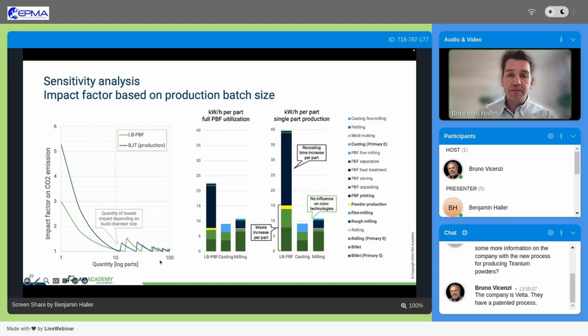But the reason is both in the material use. Even though the final part will have the same material in it, you have more waste, especially during the printing process, because there's always a certain amount of powder that ends up in the filter. So that's why the green bar here is almost twice as high. And then the blue bar is during the printing itself.